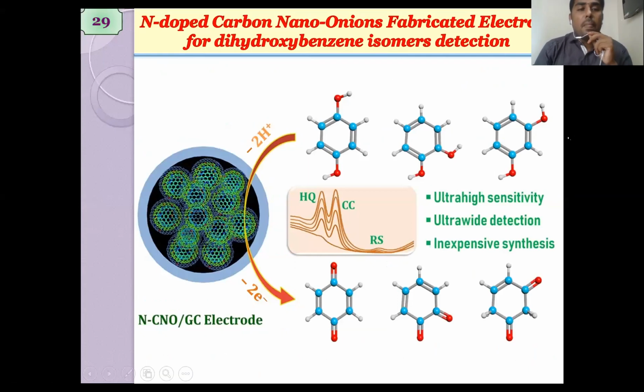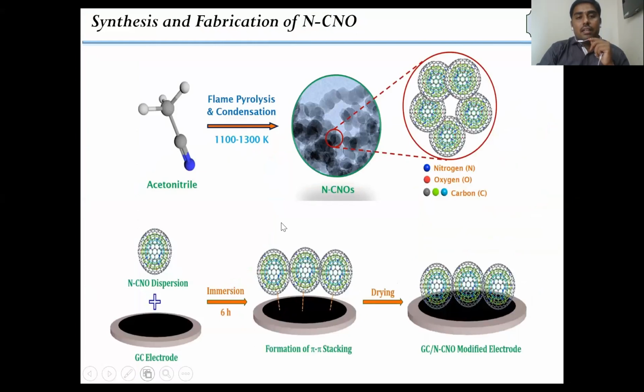The first one is nitrogen doped carbon nano-onions for dihydroxybenzene isomers detection. The dihydroxybenzene isomers are hydroquinone, catechol, and resorcinol. The nitrogen doped carbon nano-onions are synthesized from acetonitrile by flame pyrolysis and condensation at a high temperature, and fabricated on the electrode surface by self-assembly method without any linker.